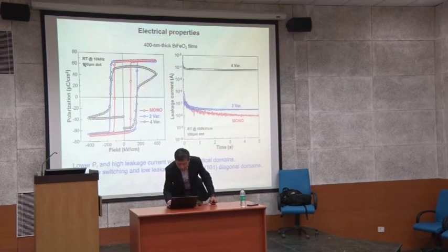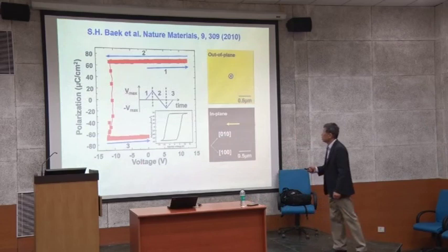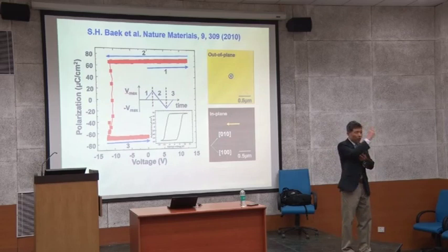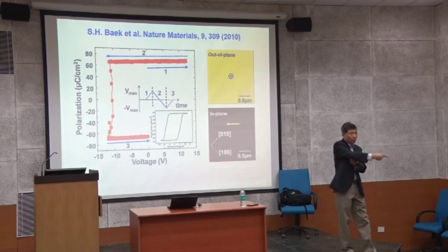So when you do this, the way you can confirm out-of-plane and in-plane mapping is that the polarization is pointing like a 54.7 degree here. So to do that, you can have a component of this or this component, and you can measure both. So it's like your piezo measurement, you can do lateral or out of plane, you can measure both of them by PFM measurement.